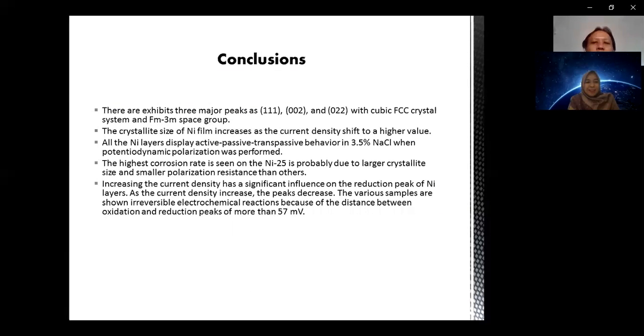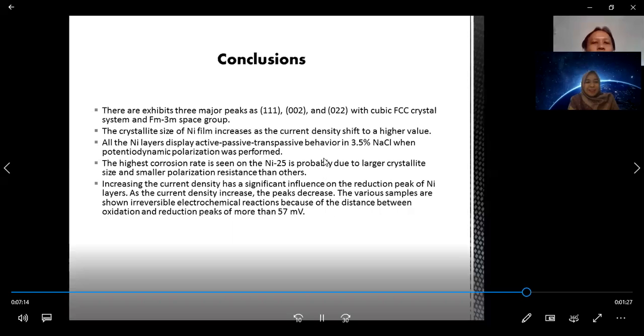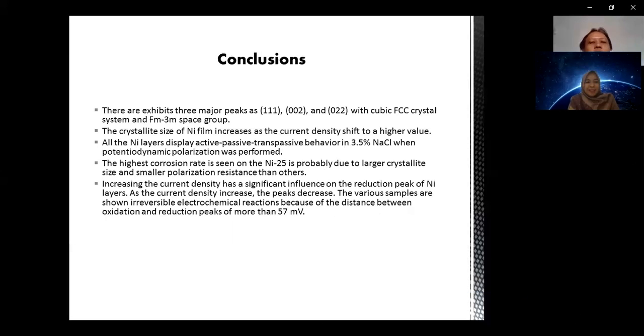In conclusion of my project, there are 3 major peaks with a cubic FCC crystal system and Fm-3m space group. The crystalline size of the nickel film increases as the current density shifts to a higher value. All the nickel layers display active, passive, transpassive behavior in 3.5% sodium chloride when potentiodynamic polarization was performed. The highest corrosion rate is seen on the nickel 25 sample, probably due to larger crystalline size and smaller polarization resistance than the others.